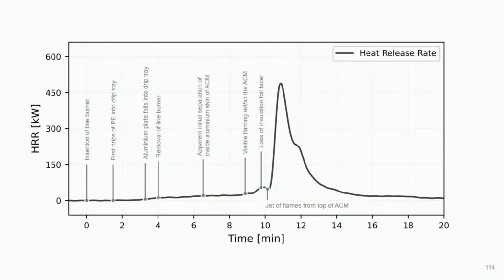from between the two aluminium plates, separation of the inside aluminium skin, very rapid and violent escalation up to the peak heat release rate, and then a slow decay over a period of a few minutes until the PE stops burning and we finish the test after 20 minutes.